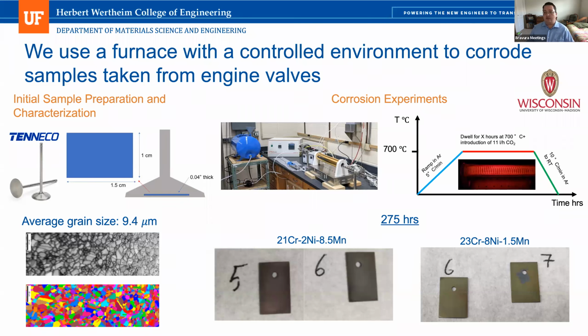And then we take those samples and we put them into an experimental apparatus that we've established at the University of Wisconsin-Madison, which has a furnace that allows us to control the gas environment within the furnace. And then we can use the furnace and go through different temperature ranges and temperature cycling and so on, and then look at the corrosion of our samples. So we then remove the samples, and then we can do microscopy and characterization of the samples after oxidation.